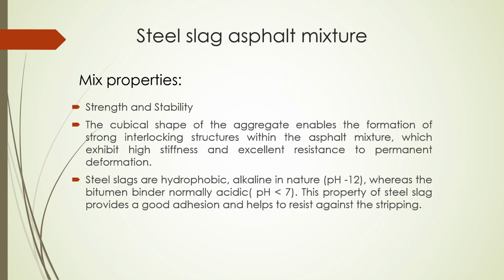Next one is steel slag asphalt mixture. Mix properties: strength and stability. Since steel slag has a rough textured surface, high specific gravity, and proper interlocking due to the angularity of steel slag aggregate, it results in better stability and resistance against rutting as well. It has a cubical shape, which is why the aggregate enables the formation of a strong interlocking structure within the asphalt mixture, which exhibits high stiffness and excellent resistance to permanent deformation.